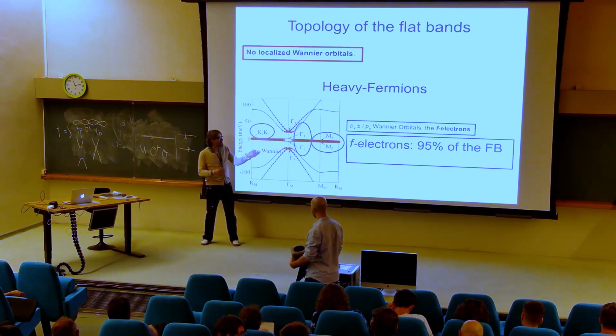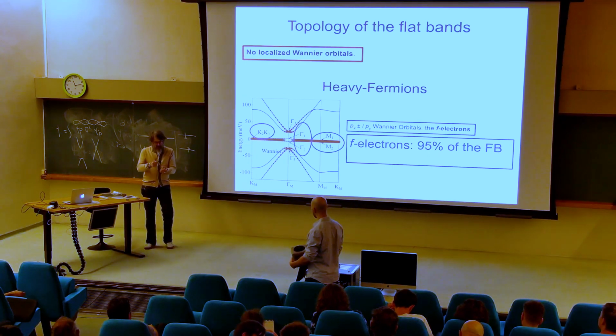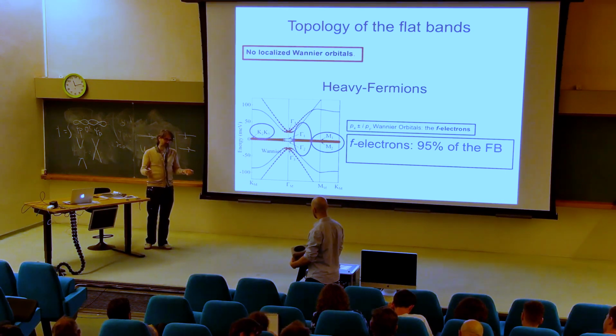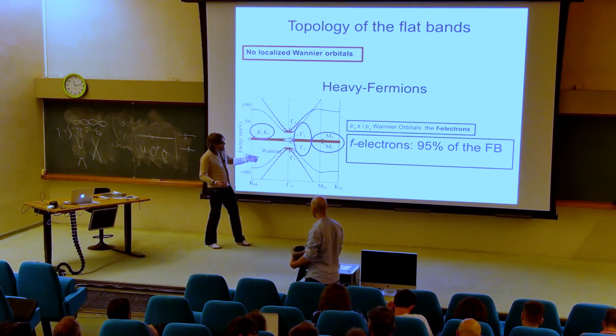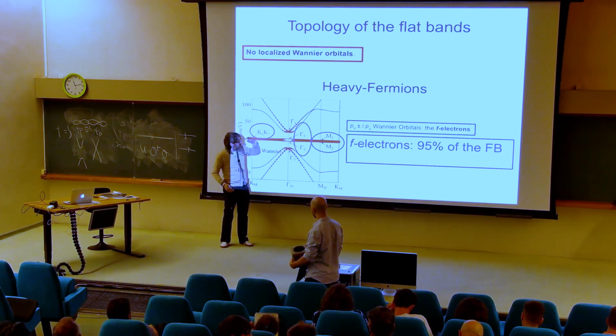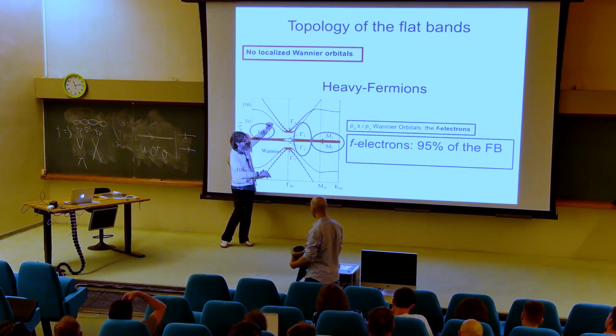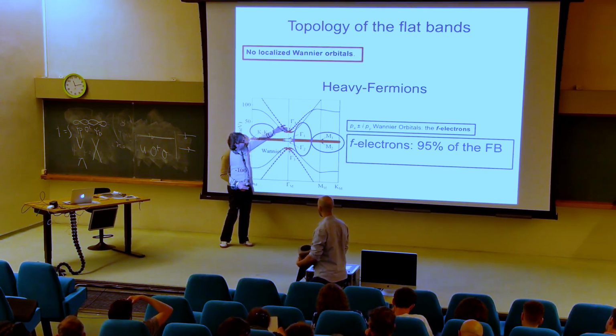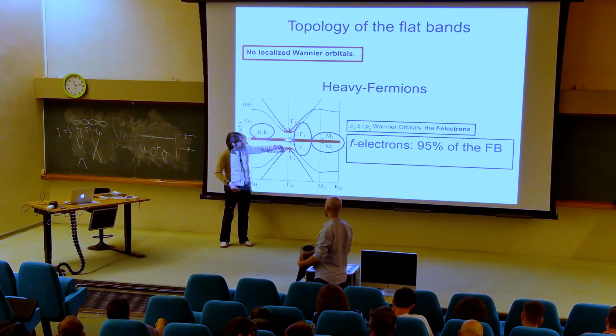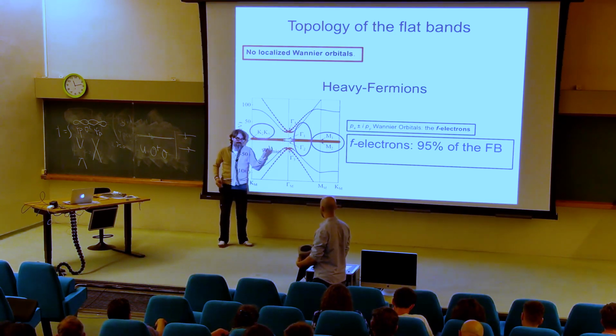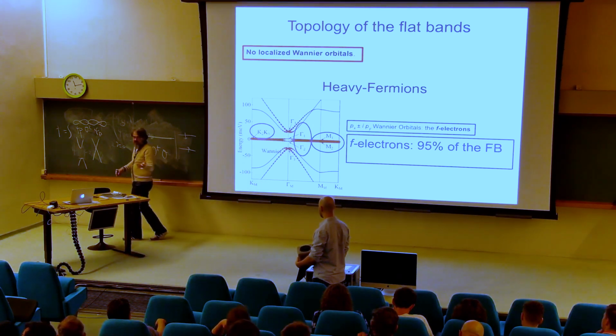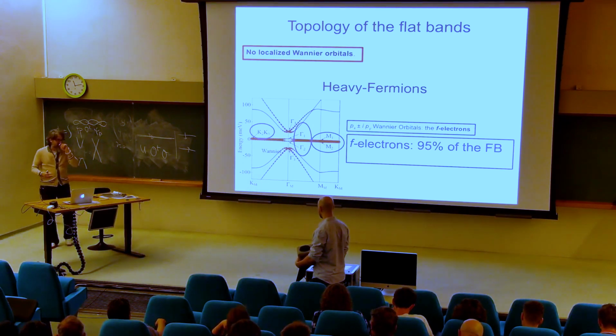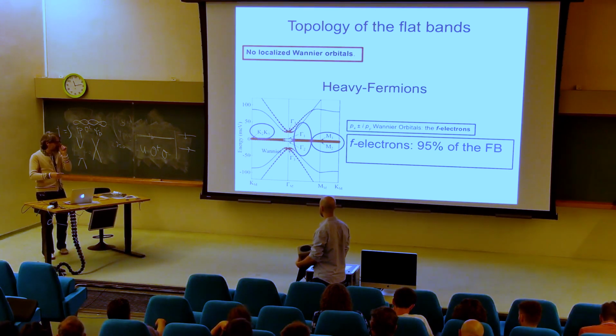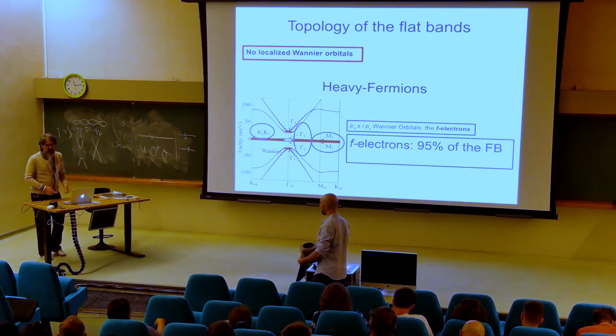So most of the time, this is just really the inversion principle. The inversion principle tells you that where you invert it, you get most of the Berry phase. Everything else, the band can be localized. So you can always kind of pawn off the topology on something else. And here, you can just do it algorithmically. You ask, in this energy window, which is Hubbard U, or Coulomb, how can I create a trivial band with these eigenvalues? And there's only one way. In some other cases, there might be more than one way, in which you have to test which one is the most localized, because they will give you the nicest Coulomb. All you want to do is put the Coulomb into the least amount of degrees of freedom that you want. So that's the algorithmic way.